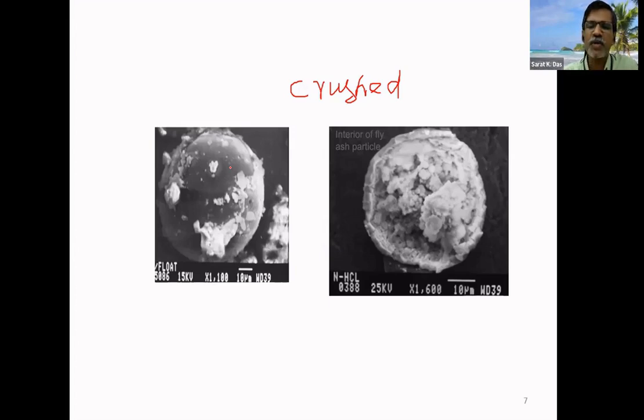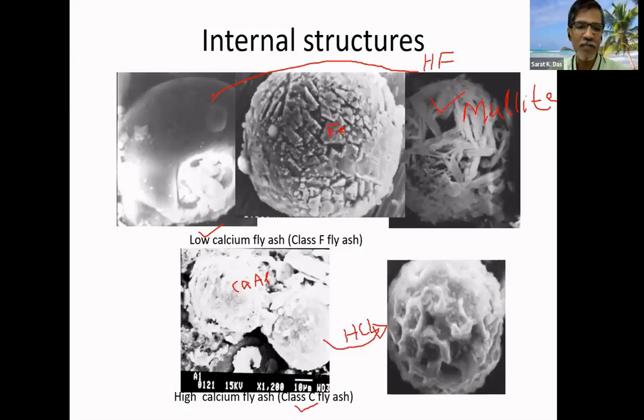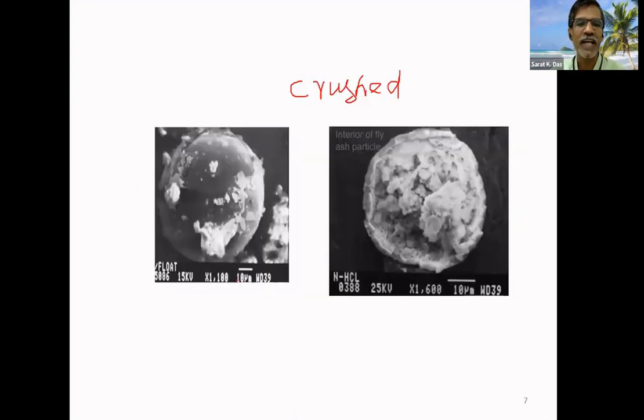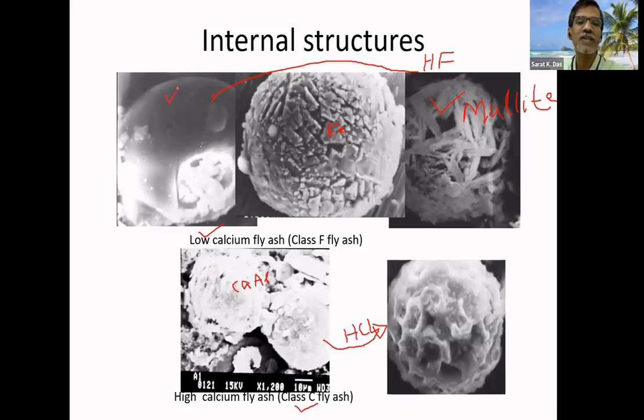So this was the importance of going for this morphological study, so that I can know if it is spherical. That's why in concrete, they call it a mineral admixture. It increases the workability, because a spherical particle will not take more water, but it can make the mix more workable. And if you see this picture, this high calcium fly ash is reactive, because this calcium is on the surface, it will react immediately. And this pozzolanic part is on the surface of this fly ash and low calcium fly ash. So if I create such alkali conditions, it can react. So all this tells the importance of this morphological study.